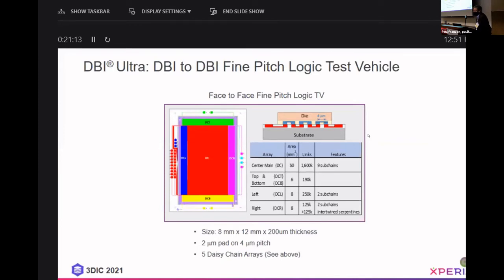This next slide shows our fine pitch test vehicle, which again, it's an 8 by 12 millimeter part. In this case, the die are 200 microns thick. We have a 2 micron pad on a 4 micron pitch and 5 different daisy chain arrays. The main chain array has 1,600,000 connections in the center of the die. And then we have surrounding daisy chains around that with fewer connections. One with interleaved connections, so we can check both continuity and leakage between the chains.